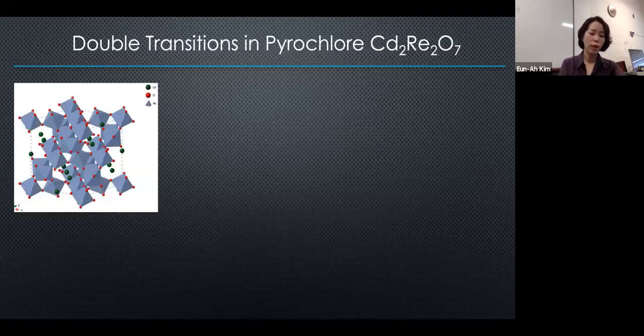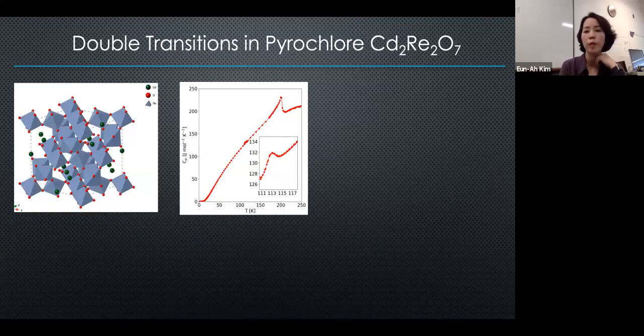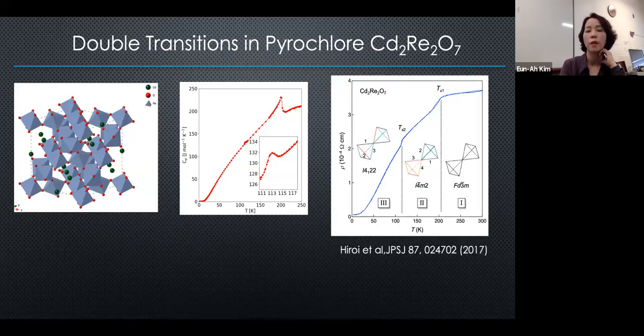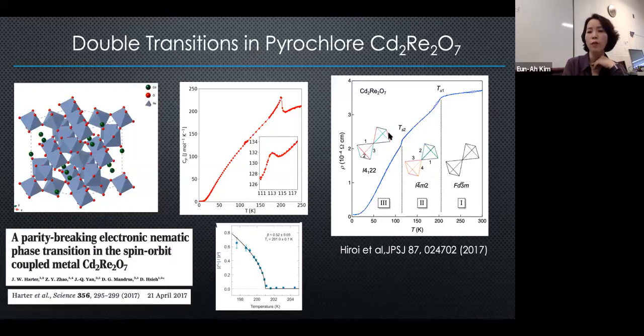So we looked at a pyrochlore material, cadmium rhenium oxide, which, with this approach, has two transitions. It has a transition that is second order and another transition at around 113 degrees. Although this is a material that's been known for a little while, it started to gain more traction around 2017, because one of these transitions, the higher temperature, 200-degree transition, had its order parameter seemingly detected by this higher harmonic generation approach.